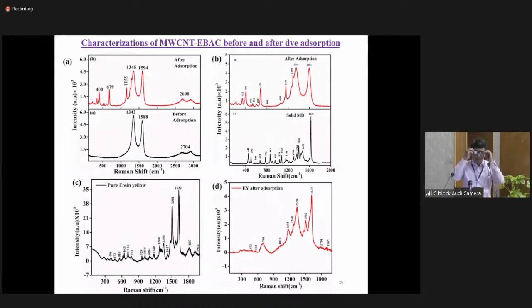And then we also characterized the material after dye incorporation, to see whether the dye has been adsorbed or not. You can see this with the help of Raman spectra. Before adsorption, there are pure carbon materials, which have a D band and G band. And then this is the spectra of methylene blue. So after the adsorption of the dye, you can see some other peaks have also been found. That means the dye has also been adsorbed on the surface of the activated carbon.